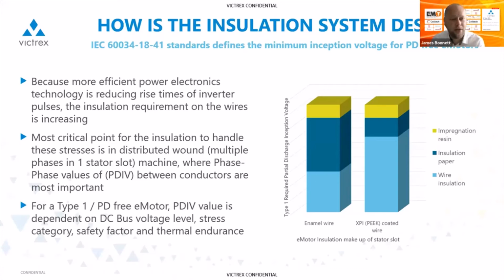The most critical point for the insulation to handle these stresses in a distributed wound configuration is that phase-to-phase value of PDIV that I showed on the previous slide between the two pairs. So PDIV is affected by pressure, humidity, temperature, but after these environmental factors, the number is driven by physical separation of the conductors, so the distance apart, and the relative permittivity of the dielectric material between the two conductors. In our scenario, though, this isn't just one material, it's several materials combined. It's the wire insulation, the insulation paper, and the impregnation resin.